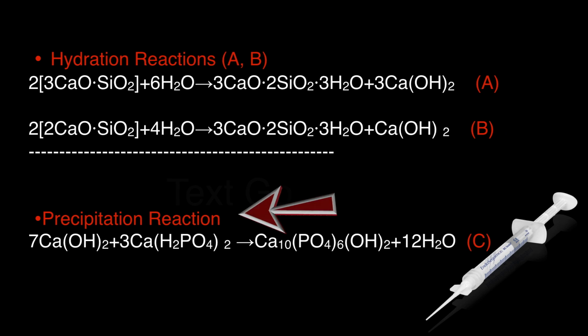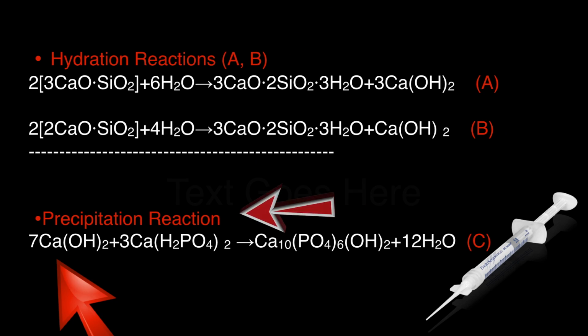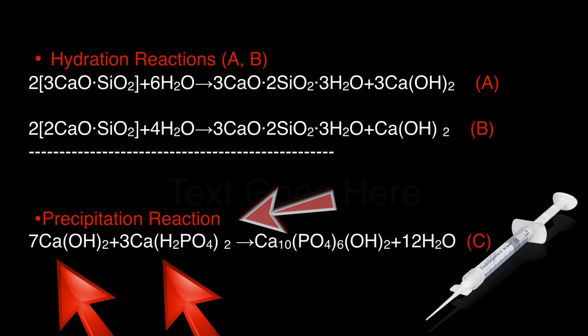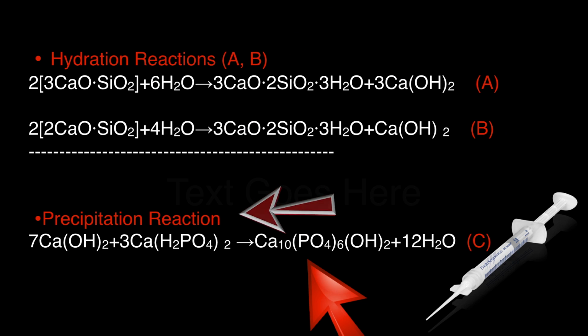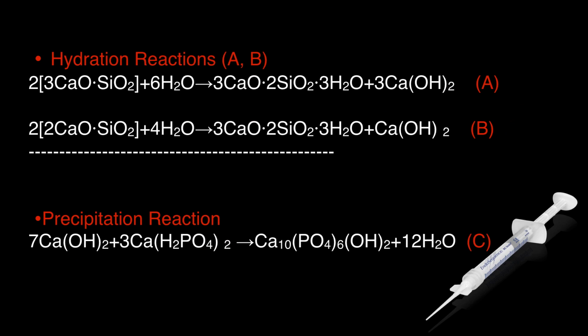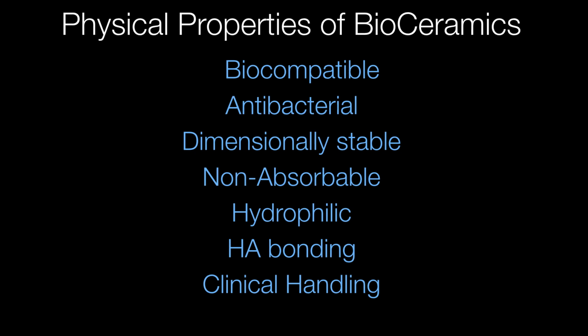And then what ends up happening is the calcium hydroxide slowly reacts with the calcium phosphate that's in the cement, and then what you end up getting is hydroxyapatite, which is the material that is found in the vertebrate skeleton and is an integral part of the bone. So we can then determine, just looking at the chemical formula of this compound, that you have a material that is hydrophilic, that is biocompatible because of the hydroxyapatite that is produced as a final reaction. It has high pH, therefore it's antibacterial, as well as it produces an environment that is conducive for bone formation.